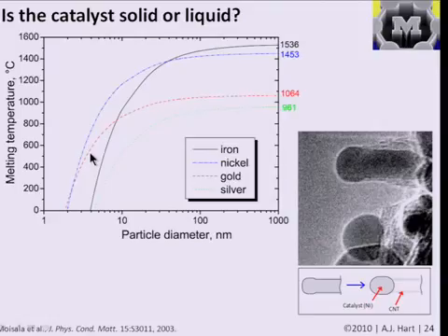You might remember the video I think we had on the first day, where this was an in situ TEM video of a carbon nanotube growing from a nickel particle. We didn't talk about melting point suppression then, but this was at about 500 C, and the metal particle was actually kind of inching along like a worm. It was changing shape. It was kind of squeezed out and then jumped forward. And it's not clear if this was entirely liquid at that state, but certainly it was compliant and could change its shape at a temperature of about 500 or 600 C.